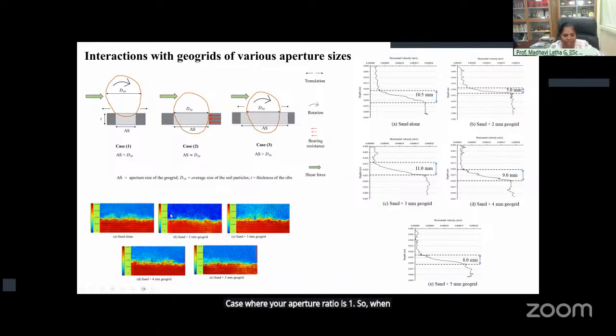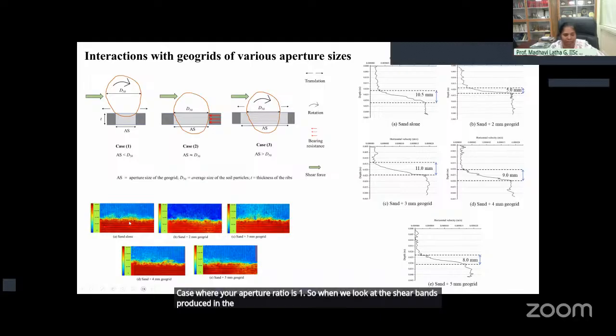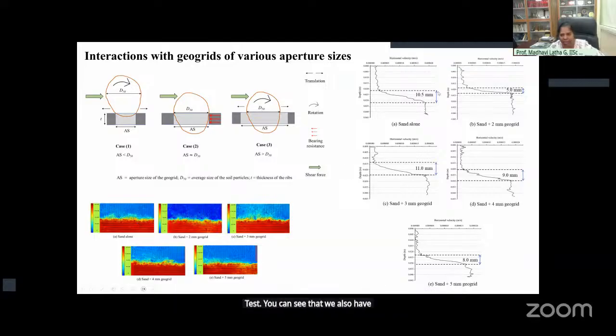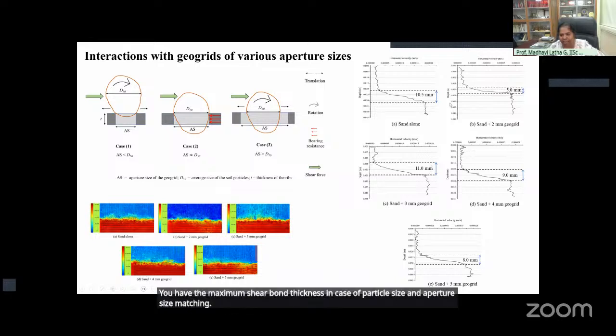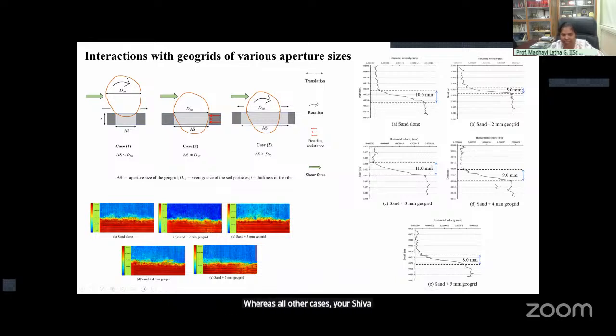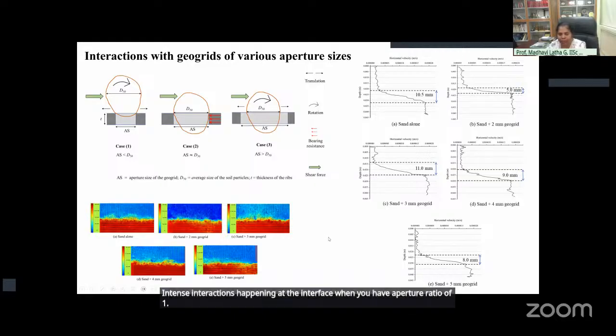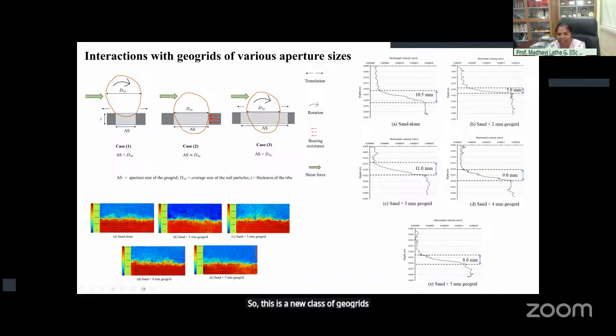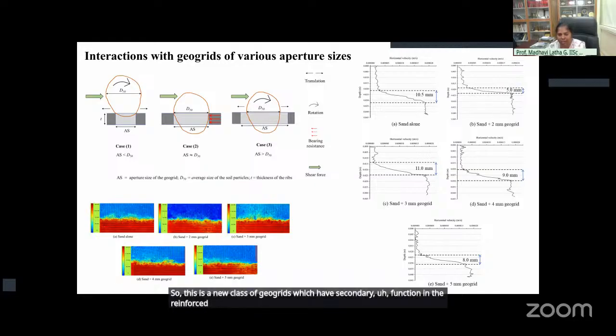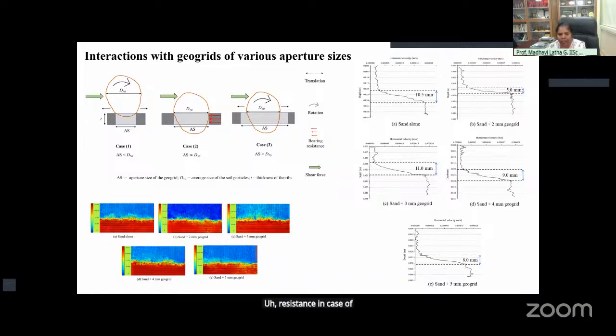So when we look at the shear bands produced, using particle image velocimetry in shear tests, we also have a comparison of shear band thickness. You have the maximum shear band thickness when particle size and aperture size match, whereas in all other cases your shear band thickness is less. This tells you there are intense interactions happening at the interface when you have an aperture ratio of 1. So this is a new class of geogrids which have a secondary function in reinforced systems that can enhance the liquefaction resistance in case of dynamic earthquake loads.